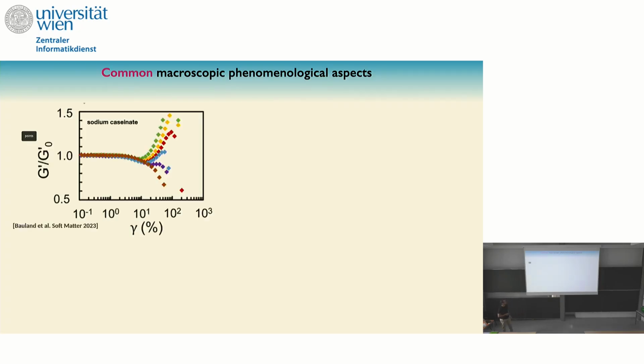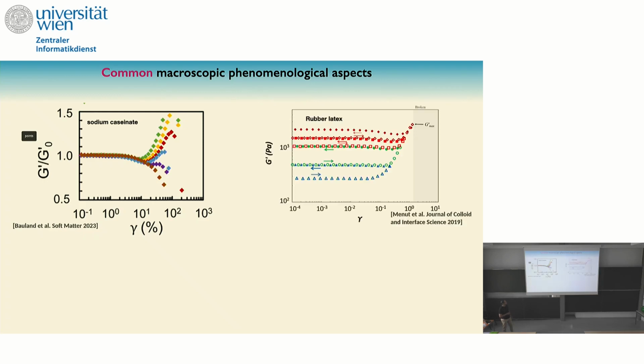All right. So if I try to see some common aspect between all these materials that have reversible or irreversible types of interactions, I can also look into the shear modulus by doing a frequency or amplitude sweep, by doing oscillation in my system and changing the amplitude, and then I would measure the modulus as a function of the strain that I apply. Again, for casein gel, here is the modulus, not the stress, as a function of the strain. So you get a linear regime, and then if you change the volume fraction of the system, you get this strain hardening. This strain hardening is also seen in other types of material, like natural rubber latex material, where the modulus also at some point would increase dramatically with the strain, as if the material is trying to resist the deformation that you apply.